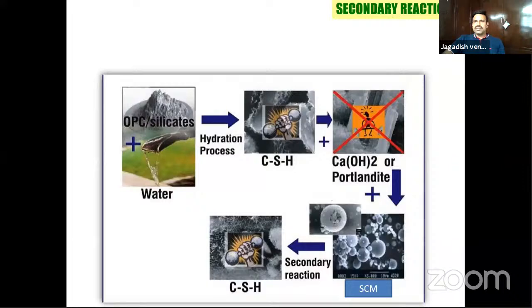What if you add mineral admixture? You know the basic reaction. When you add water to the cement, the basic hydration process will happen. The final product is what we call calcium silicate hydrate, that is CSH gel, which gives strength to the concrete. And there is a remaining amount of calcium hydroxide, or Portlandite, as we call it.